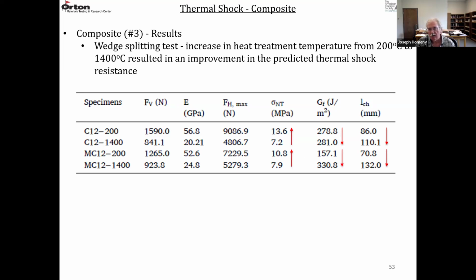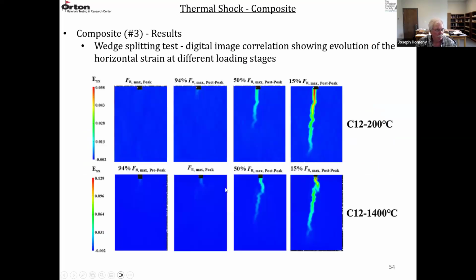And then the characteristic length increases as you increase the curing temperature from 200 to 1400. This one's pretty modest, 86 to 110, but this one again almost doubles, 70 to 132. So what this is saying is that this material, MC12, the finer grain size distribution, should have better thermal shock resistance.